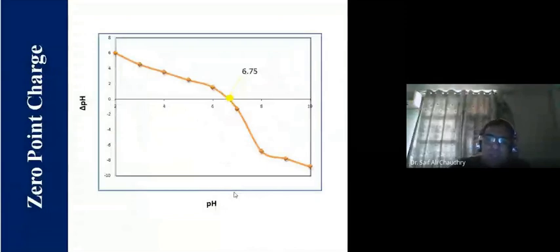Now, once the composite was established, we tried to know the surface charge, and at neutral conditions it was 6.75. It means the ZPC, zero point charge, was 6.75. At this it is neutral, but after this it is a negatively charged surface, and before that it is a positively charged surface. Therefore the material can be very effective around 6.75, right?